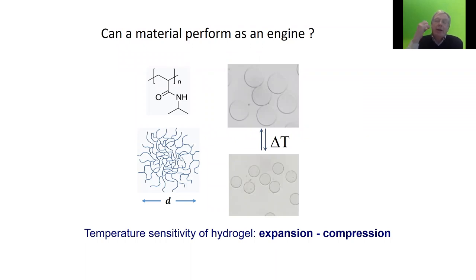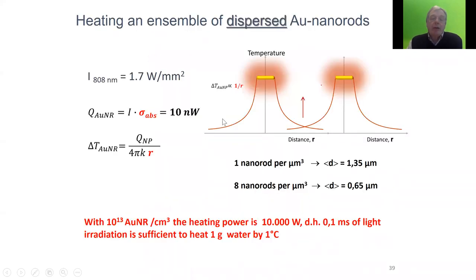For an engine, you would like to have volume changes in there, like in a combustion engine. And one of the material volume changes is the responsive hydrogels. And at low temperature, the hydrogels are strongly swollen. At high temperature, the hydrogels collapse in there according to the lower critical solution behavior of these type of water swollen materials in there, caused by the hydrophobic interaction.